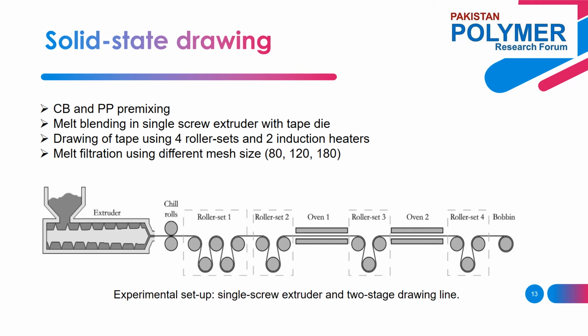In this research, 1.5 percent of carbon black and isotactic polypropylene pellets were premixed before the polymer processing step. All isotactic polypropylene grades were processed using a single screw extruder attached to a melt pump and a tape die of 15 millimeter width and 1 millimeter height.